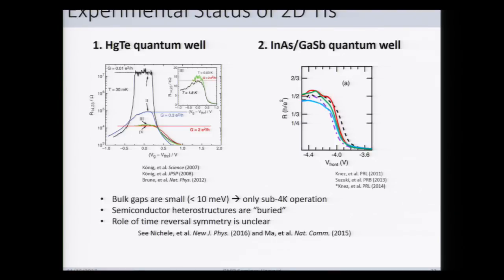One is that the bulk band gaps are relatively small. That means the interior of the 2DEG has a small band gap, and this has resulted in relatively low temperature operation to access the physics of the edge modes. The semiconductor heterostructures are buried by a capping layer, and this makes it actually difficult to interface the 2DEG with, say, some interesting other system like a superconductor. And then finally, the role of time reversal symmetry is not entirely clear.